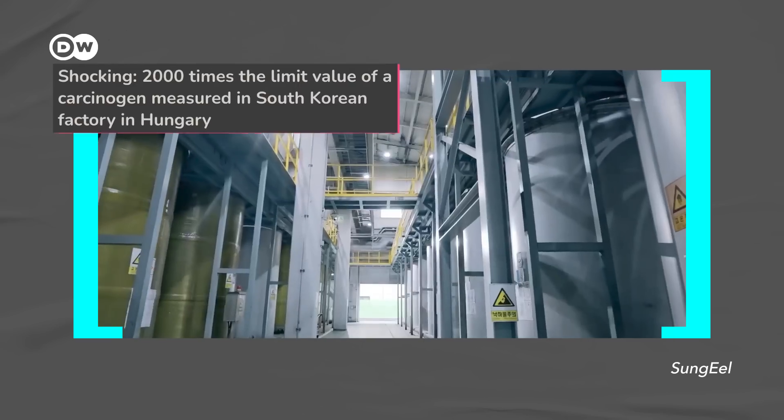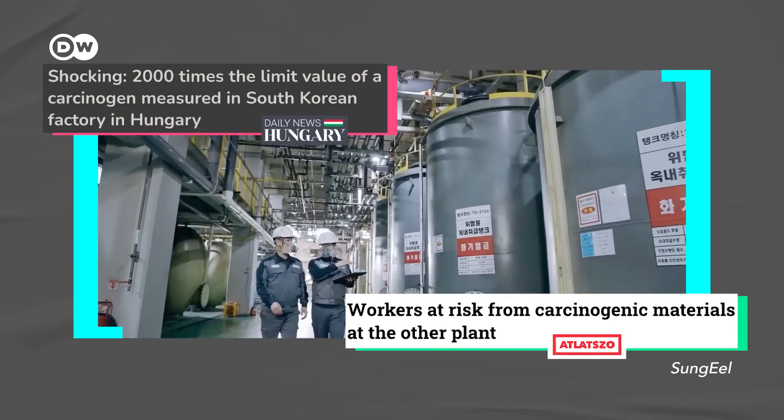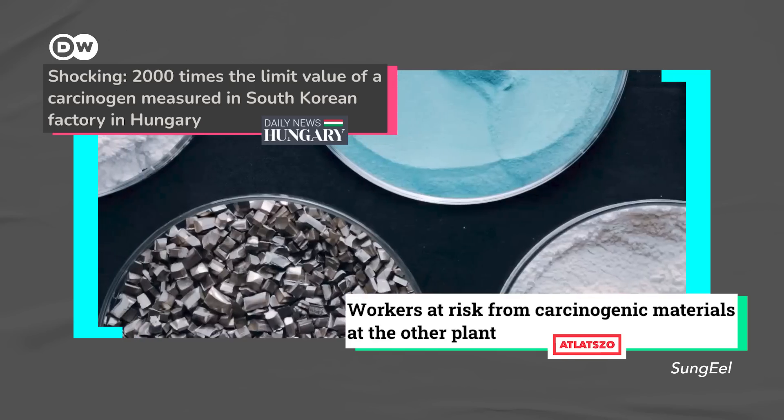There is kind of a small issue. Depending on the acid used for leaching — in this case sulfuric acid — there may be some evolution of H2S and possibly HF formation. That's problematic and definitely something you need to look into when upscaling. The acids, solvents, and leachates are also not great for the environment. However, research into organic acids — more green, biocompatible acids — is underway, though still not as advanced. And if you don't work cautiously, you get headlines like this: a factory in Hungary recorded high levels of cancer-causing heavy metals in the air and had difficulties filtering its exhaust gases. Bye-bye environmental benefits of recycling.